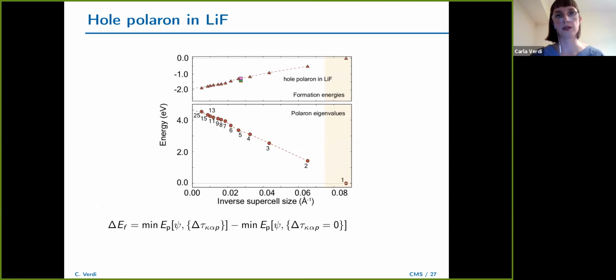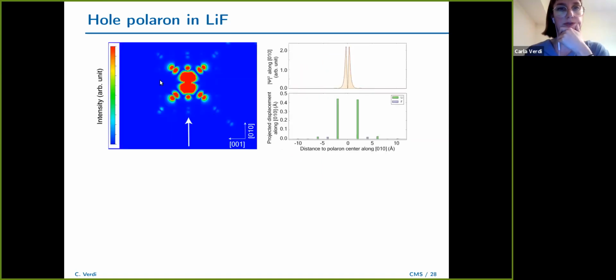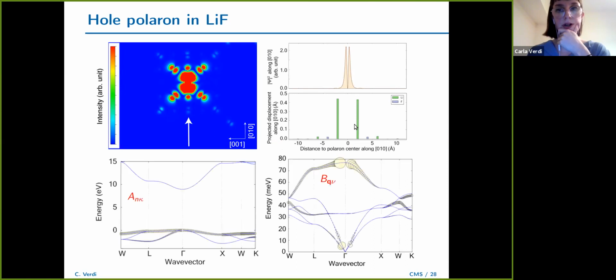So the theory is perfectly symmetric for holes or electrons. So we can do calculations for hole polarons. These are the formation energies. And this is the eigenvalue. So the eigenvalue is positive because it's measured with respect to the valence band top. So you see that this is now a small polaron. We can achieve localization already with a 2x2x2 supercell. Sorry, this is a projection of the charge density on a plane, and these are the atomic displacements as before.